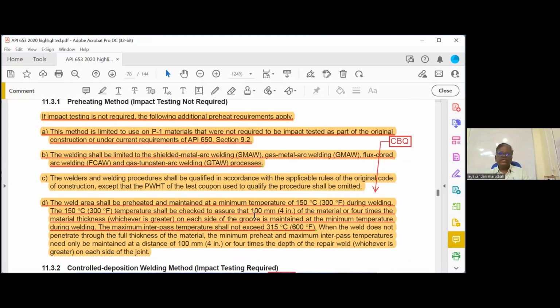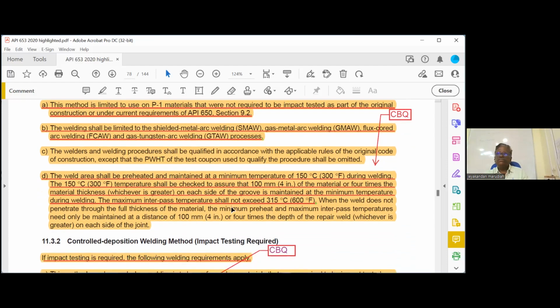The temperature shall be assured 4 inches or 4 times the thickness, whichever is greater, on each side and maintained. The maximum interpass temperature shall not exceed 600 degrees Fahrenheit. These are not important. Generally, this area may have only one question.